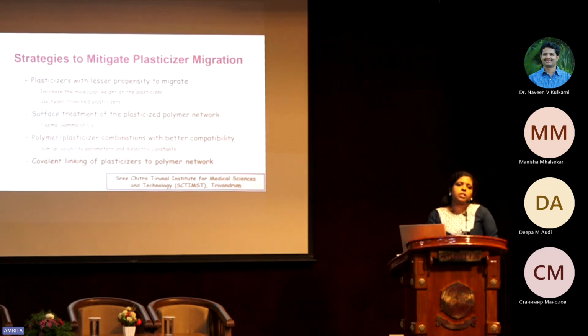So there are different strategies used to mitigate plasticizer migration and leaching. For example, plasticizers with a lesser propensity to migrate, by increasing the molecular weight of the plasticizers rather than using low molecular weight systems. The use of hyperbranched plasticizers is one strategy. Another strategy is surface treatment of the plasticized polymer network by means of plasma, gamma, UV radiation, etc. And there are also strategies that introduce polymer-plasticizer combinations with better compatibility, for example, with similar solubility parameters and dielectric constant. And the most important strategy is the chemical cross-linking of plasticizers in the polymer network.